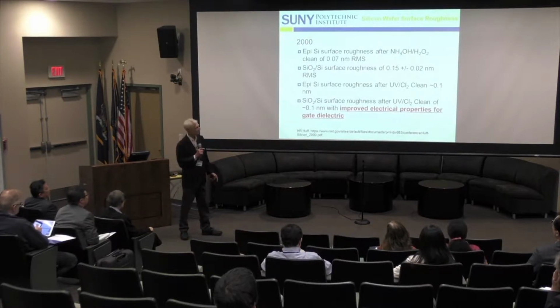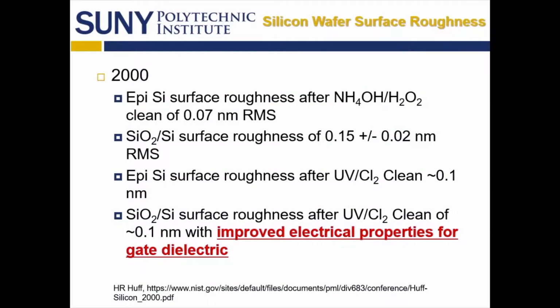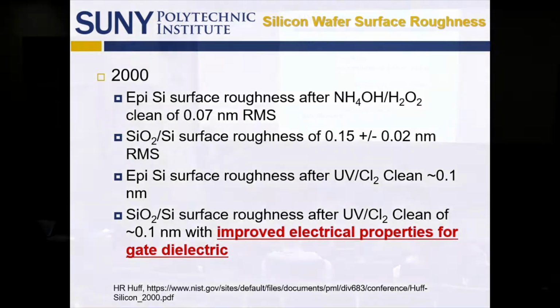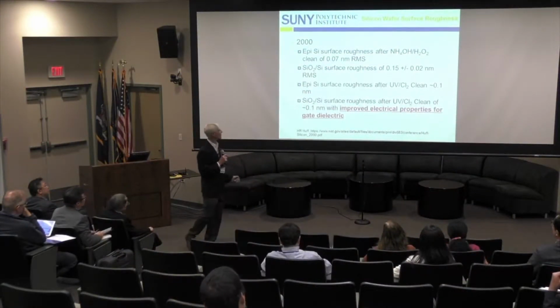But if you're to think about this in terms of something that's easy to put into a roadmap, like the International Technology Roadmap for Semiconductors that used to be around, and at the time was a very well-known instrument of exchange of information, it came up that you could specify incoming epi silicon surface quality with RMS, and that was after an ammonium hydroxide, hydrogen peroxide clean, for less than an angstrom. And people spent a lot of time characterizing different silicon suppliers' wafers, both epi wafers and polished silicon wafers. And they would look at a thin silicon dioxide layer and what the roughness was. They found that it was a small bit rougher, consistently, in different labs around the world.